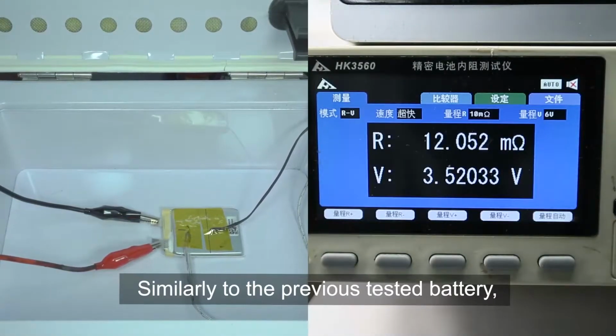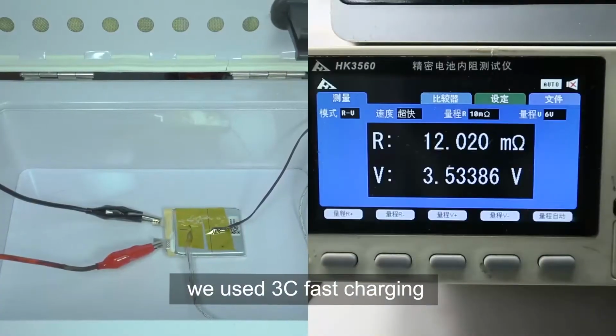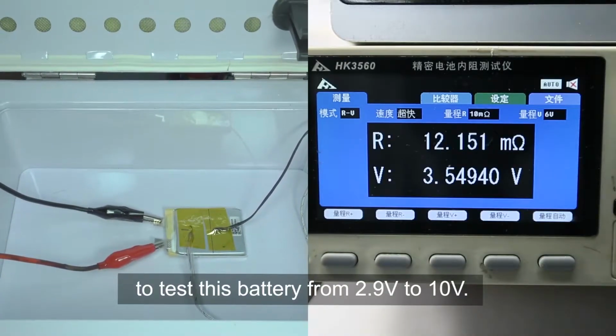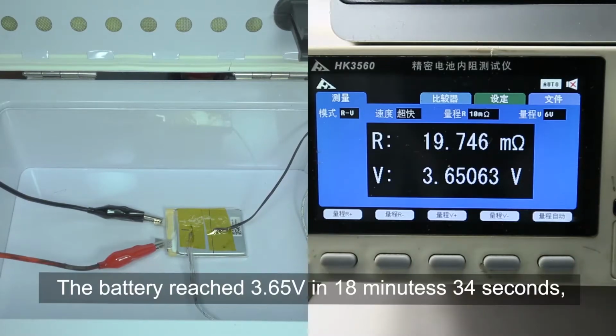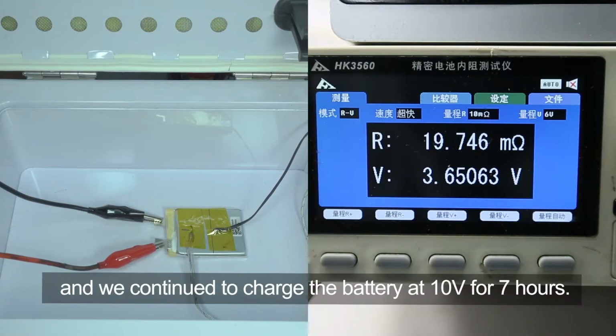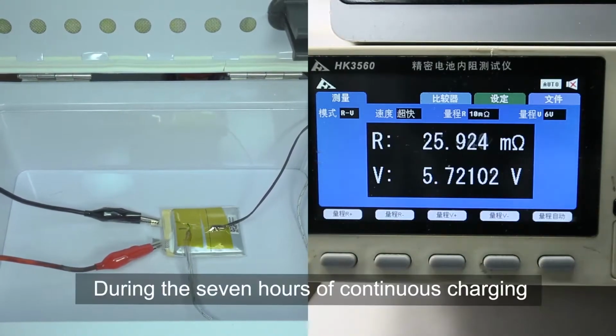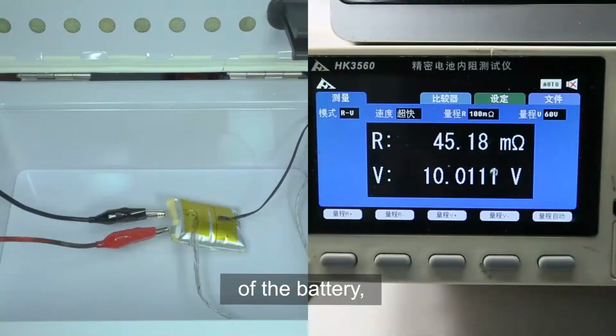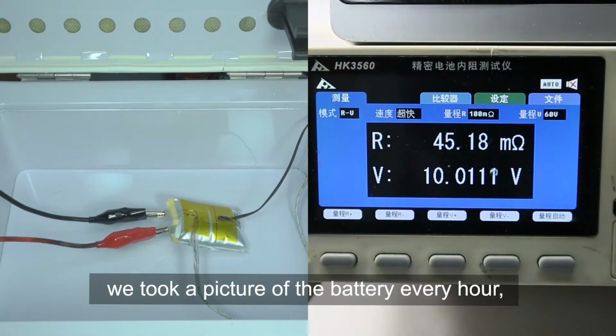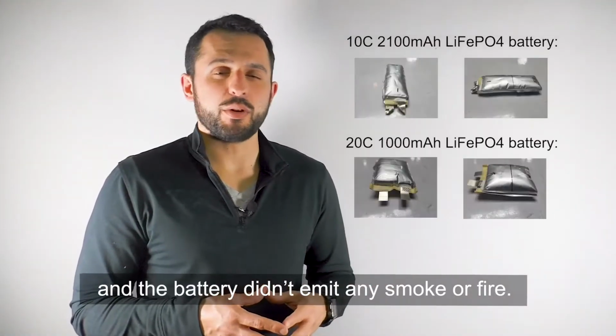Similar to the previously tested battery, we used 3C fast charging to test this battery from 2.9 volts to 10 volts. The battery reached 3.65 volts in 18 minutes and 34 seconds, and we continued to charge the battery at 10 volts for 7 hours. During the 7 hours of continuous charging of the battery, we took a picture of the battery every hour, and the battery didn't emit any smoke or fire.